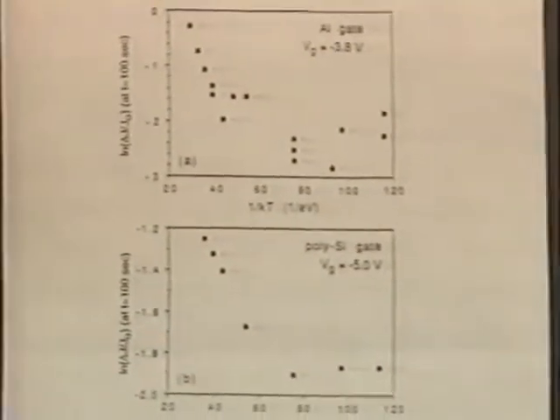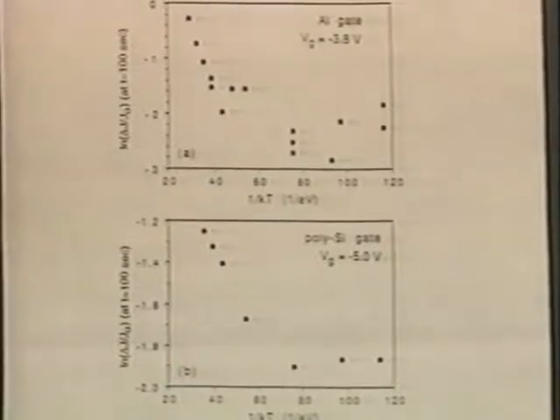What kind of effect, how can you describe this? I want to tell you about a paper I saw in Journal of Applied Physics where some people were trying to really stick with an IBM model where there's some diffusion of neutral species, and they said, oh, that must be taking place at high temperatures. After all, diffusion's thermally activated. That's what we're seeing at high temperatures. And oh, well, let's come up with an entirely different model or mechanism to explain what's happening at low temperatures. But we've got to hold on tight to this neutral species diffusion thing because some very important person thought it up. And so we'll hold on to that and just come up with a whole second model for the low temperature.